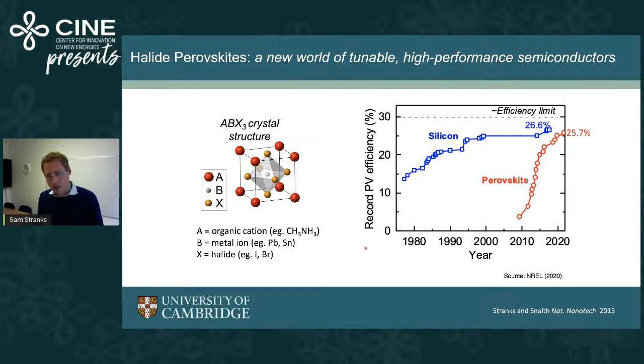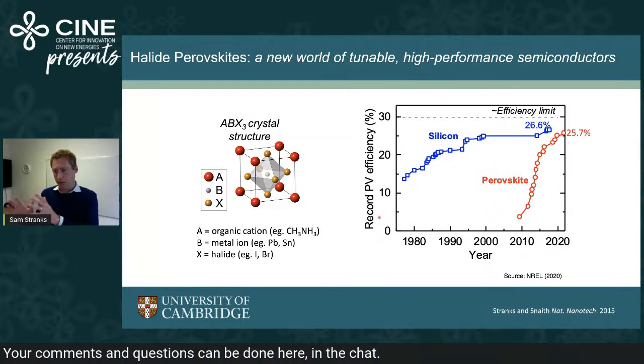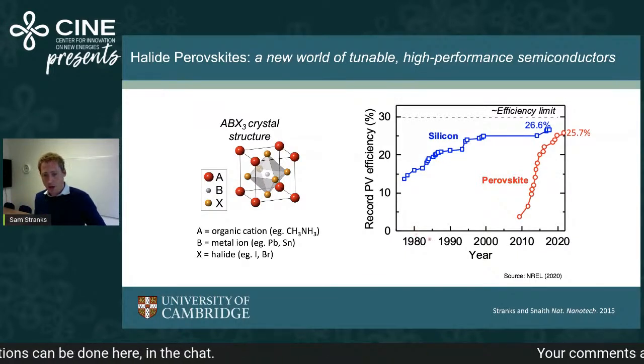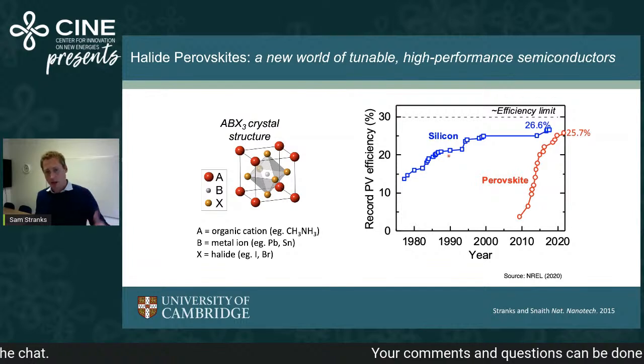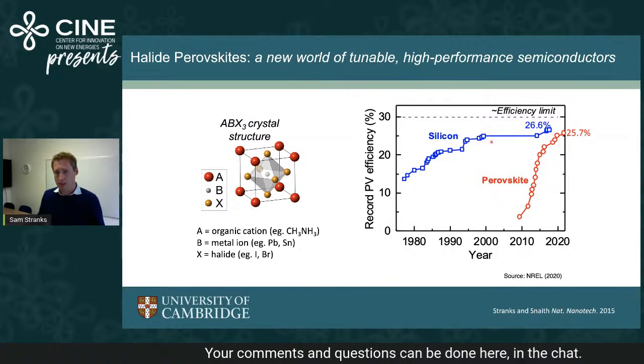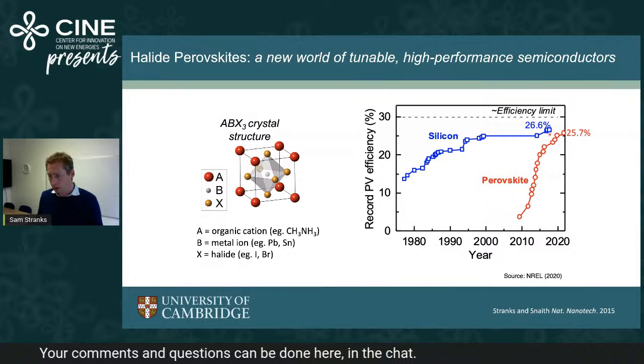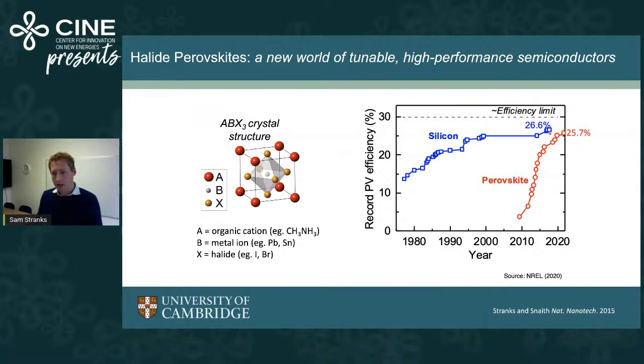On the right, this really shows why the excitement and the rapid progress in this field. This is a plot showing the power conversion efficiency of solar cells from these materials, thinking about converting sunlight to electricity, and the efficiency of that over the years. You can see silicon, the market-leading technology, has improved steadily, somewhat slowly, but it is now a very good efficiency. It's a very stable technology. But you can see just how fast the perovskite efficiency has improved, and it's now 25.7%. It won't be surprising if it overtakes silicon even this year or maybe early next year. So there are some really exciting trajectories there for these solar cells.